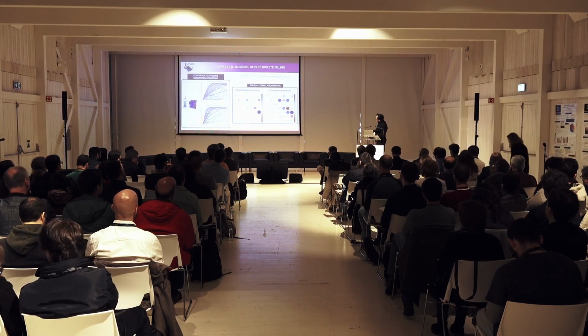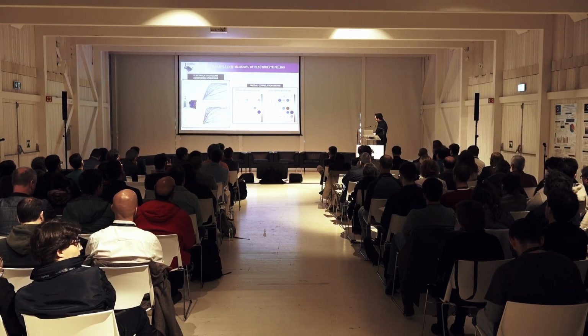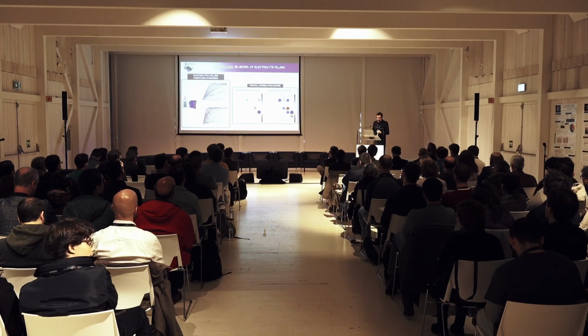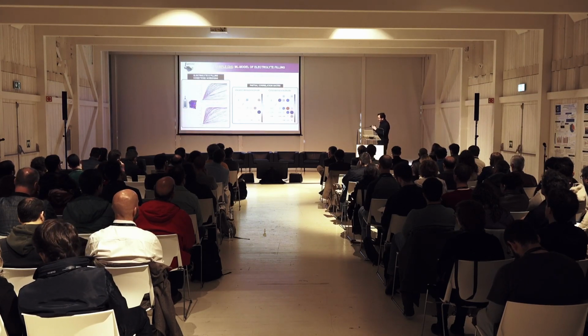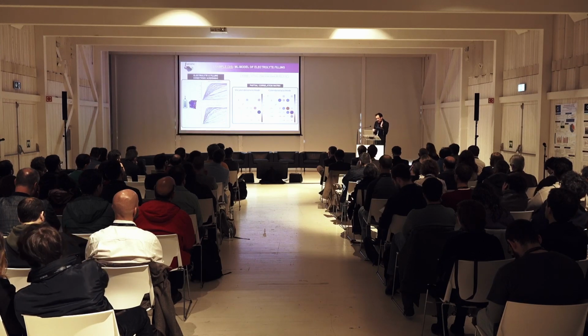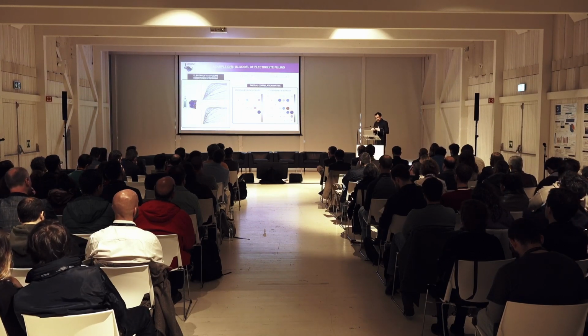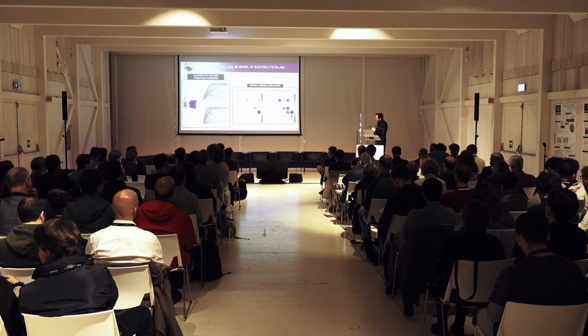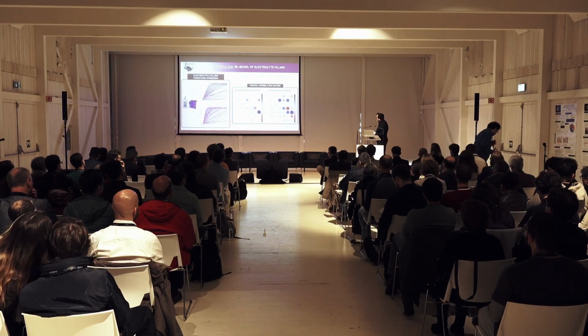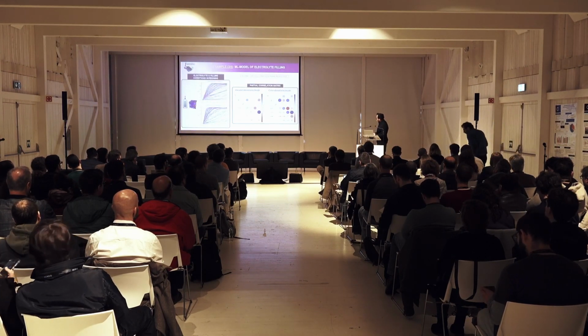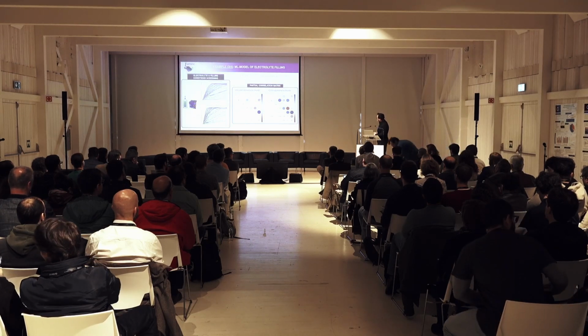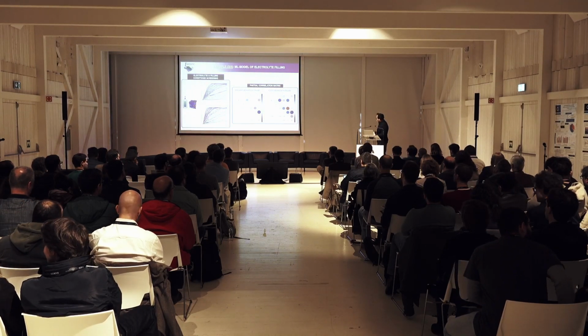And then you can establish, based on these simulations, partial correlation matrices, which are very useful to understand how these input parameters that you can control at experimental level will impact the electrolyte infiltration efficiency, right? For instance, if I pick one example for a calendared electrode simulation using this machine learning framework, if I increase the viscosity of my electrolyte, it is going to take more time to fill the electrode, right? And so on and so forth.